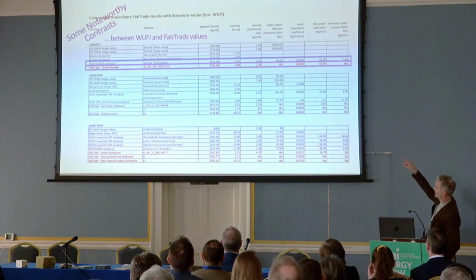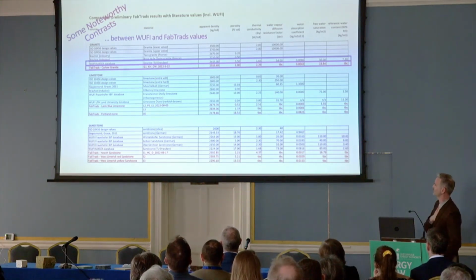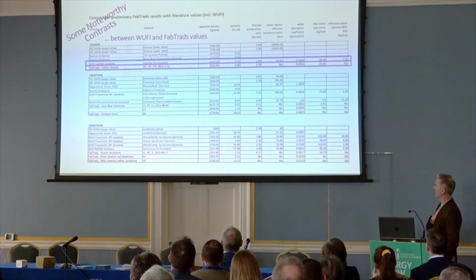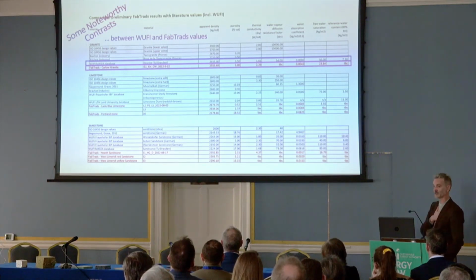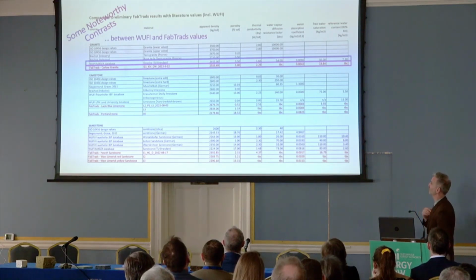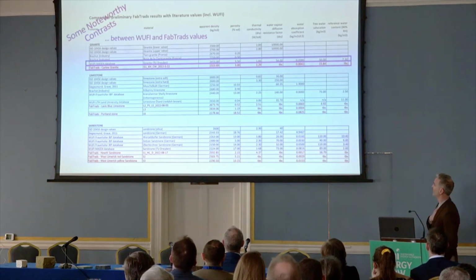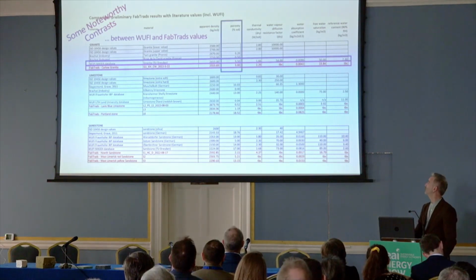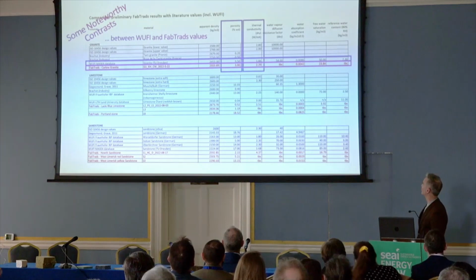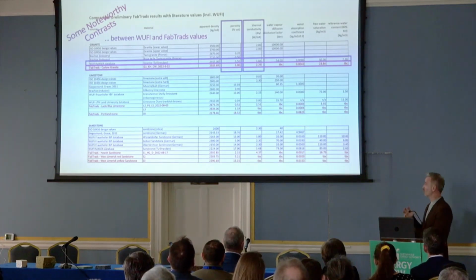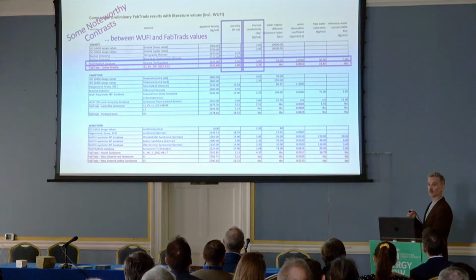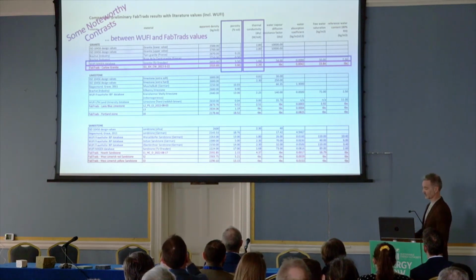At the top of the two highlighted materials is the granite that exists in the WUFI database, measured by TU Dresden. That has a porosity of 9.5% per volume of material. When we did our tests on Carlow granite, taken from the house that I showed earlier, we got a porosity of 3% per volume. The thermal conductivity value is higher because with fewer pores, it's more dense. More dense materials have a better ability to transmit heat, so we get a higher thermal conductivity.